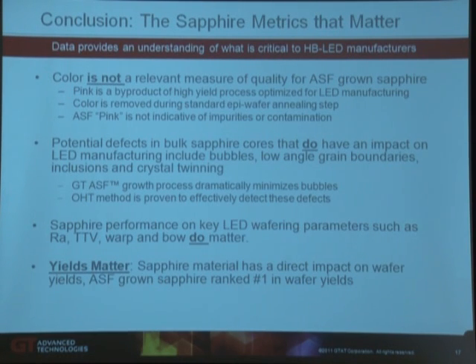So in conclusion, what does matter based on both of these studies? Color is not a relevant measure of quality for ASF grown sapphire. Pink, or the light pink hue that you see, is a byproduct of a high yield process optimized for LED manufacturing. Color is removed during the standard epi wafer annealing step, and ASF pink is not indicative of impurities or contamination.